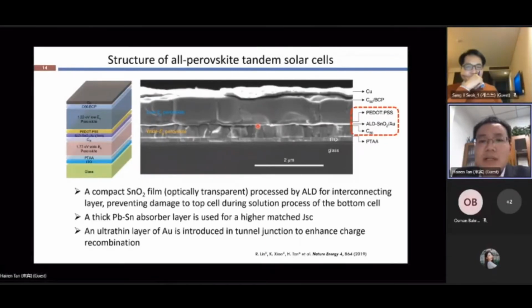So we need a solvent barrier layer. And this barrier layer is also used as a tunnel recombination junction in tandem devices. So what other researchers did before in the community is that they have to use a very thick ITO layer in the middle of the two subcells to prevent the solvent diffusion. But this very thick ITO layer generates very high optical losses, and also it generates a very high leakage current in the tandem devices that will limit the performance.